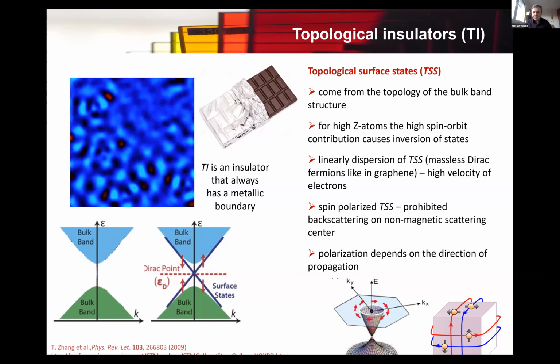Now we must understand that these surface states, which we call topological surface states, are due to the bulk band structure, not due to the surface structure. So for that reason, they are very robust. Just introducing some impurities on the surface wouldn't kill these topological surface states. This is important to understand. And normally that effect comes up only for compounds with high Z atoms, where we can expect high spin orbit coupling contribution. And that then would cause the inversion of states, which actually is required for this topology.